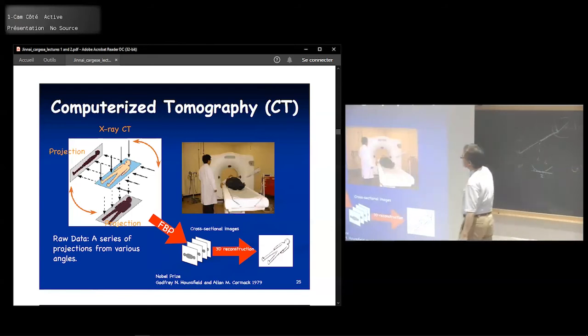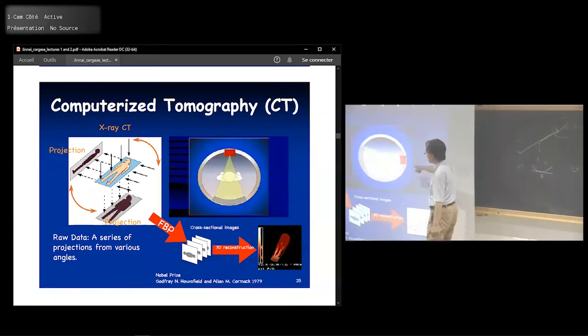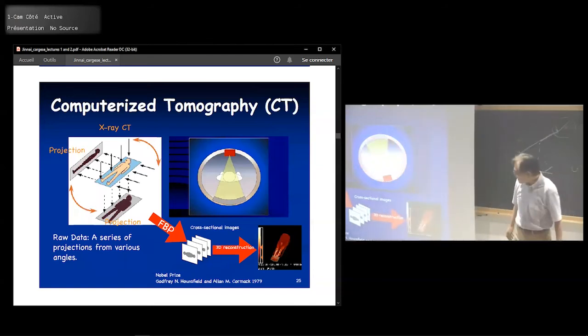So the principle is here. It's a CT. So you are the sample, and what this instrument does is there's a combination of the X-ray source and the camera, and this combination rotates around the sample. That means the instrument takes projections from different angles. That's the raw data. And then using filtered back projection, which I would like to explain a little bit later, you can reconstruct the cross section of the sample and then stack them together to make the three-dimensional image of your sample. That's a very, very naive way to explain how we do the three-dimensional imaging. Okay.